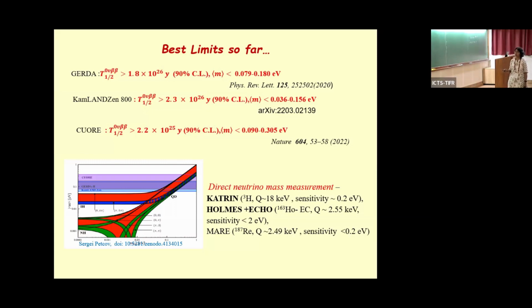These are the various limits available. I just want to mention in passing that there are also the direct neutrino mass measurements. Like KATRIN, which is looking at tritium beta decay with a low Q value, so the measurement of the endpoint energy can be obtained, and they expect a sensitivity of 0.2 eV. So that is going on. MARE is not running now, but HOLMES and ECHo are both looking at electron capture in holmium, which again has a very low Q value. So they expect to get lower sensitivity.